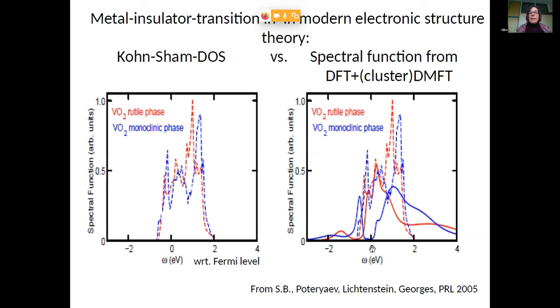In the insulating phase, you indeed open up the gap. So we are really looking now at the spectral function that we expect for the material. We open up a gap and we have a relatively well-defined peak here, which is though closer to the Fermi level and the satellite feature of the metallic phase.